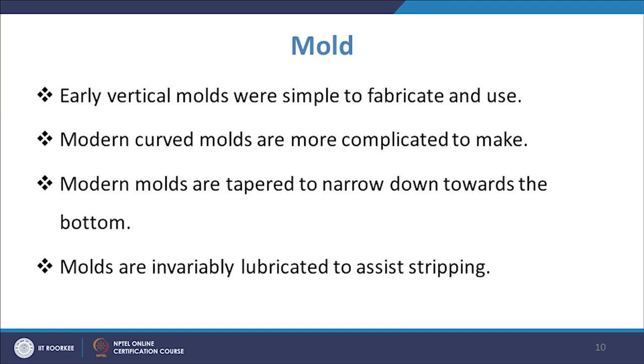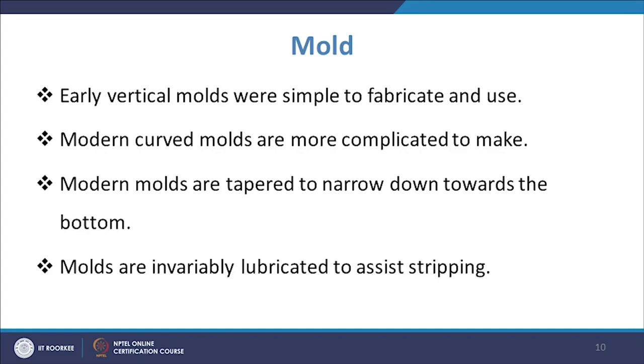Earlier we had vertical molds, and nowadays we get curved molds, which are complicated. Modern molds are tapered to narrow down towards the bottom, basically to account for shrinkage, because the metal which is solidifying has higher density. So there will be shrinking of the metal, and to account for that, some taper is given in the mold. That is another careful calculation which needs to be done to avoid any kind of defect in continuous casting.